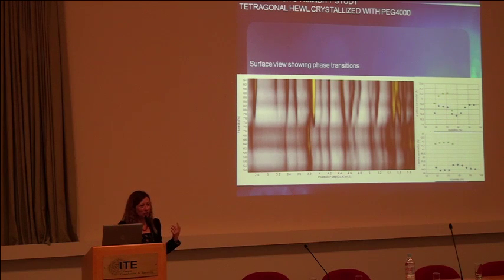After lysozyme, we continued with around 10 different enzymes and proteins in general, and in most of them we observe drastic transitions. So it's an axis that we consider very important, not only for the pharma industry to observe the stability of a drug upon environmental and storage conditions, but to see how humidity, the levels of water, modifies structures of proteins, as it has done in DNA, for example. And this is how one polymorph of DNA from A to B to Z, these things have been observed already. So we consider humidity as a very key parameter for protein structures.